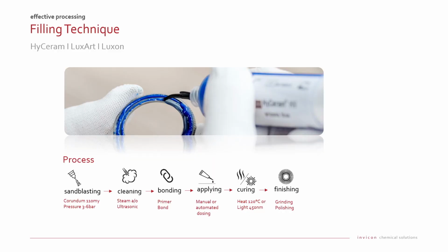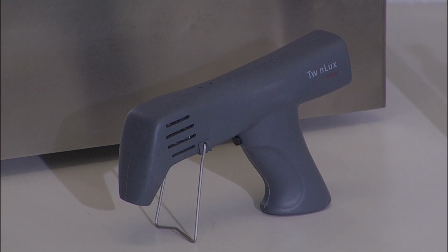Next, also important is this overfilling. That means we always have to overfill our jewelries. We cannot fill only until the surface, because we need to grind and polish our materials. So also, of course, with HyCeram we overfill a little bit, then we cure it out, and then we go for grinding and polishing. And again, the difference between light curing and HyCeram is the curing process. That means light curing materials with the blue light, and HyCeram with the Ceram power device with heat and pressure. Good. So I would say we have a short video.